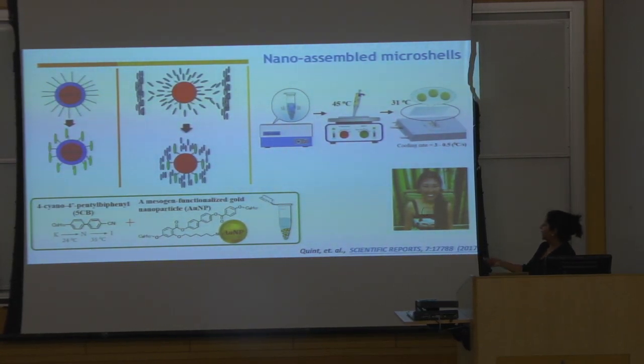So we said, OK. They showed us how they make them. We tried. That didn't work out. They make the ligands. We do the ligand exchange on the nanoparticles. And then we follow the same procedure. We put them in, we sonicate them for hours, put them on a hot plate, cool it down, the same procedure we did that gave us aggregates. And this work was done by Makiko.